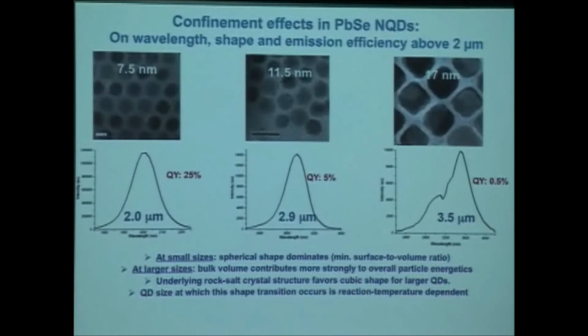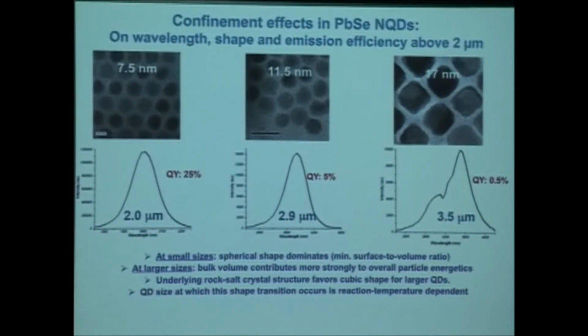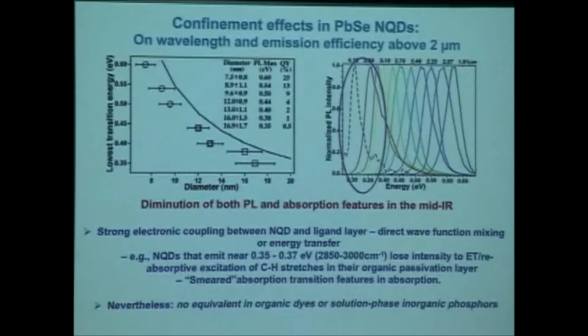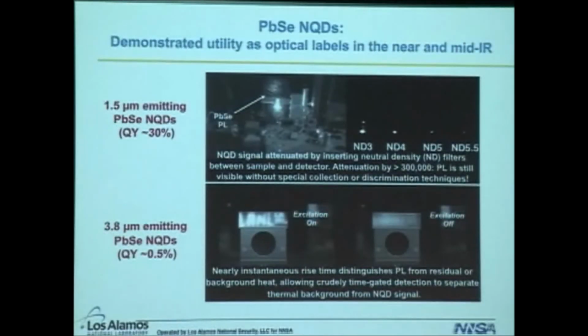Our efficiencies at 3.5 microns were only 0.5%, but frankly, that's pretty good if you think about the dye IR26, which is your most common near-IR molecular dye. It has a quantum yield of 0.5%, but that's at 1.1 microns, not at 3.5. There's nothing that's like that. So this is quite unusual in that respect. So, significant tunability, I'm going to skip this.